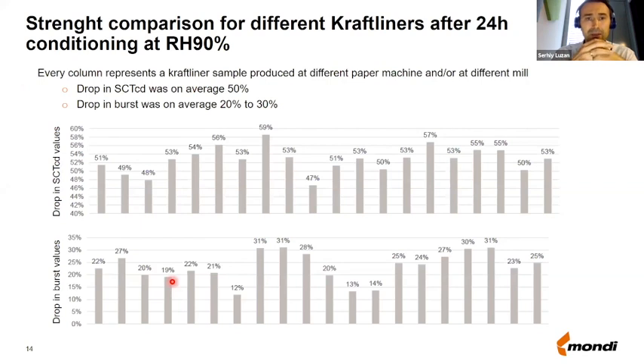However, before, we spoke about direct contact with water. I was telling you before that some people are trying to evaluate how good the paper is for humid conditions by conditioning the paper at 90% relative humidity and then testing the paper either for SCT or for burst, depending on the test required. Quite interestingly, we also did a lot of tests like that, and we found that the behavior of papers is quite similar. We took different kraft liners produced by different suppliers on different paper machines, conditioned them for 24 hours at 90% relative humidity, and then tested the SCT and compared how much the SCT drops after conditioning compared to original values. And we noticed that on average, the drop is actually close to 50%.